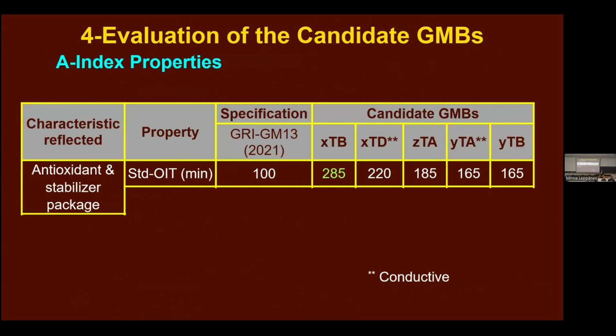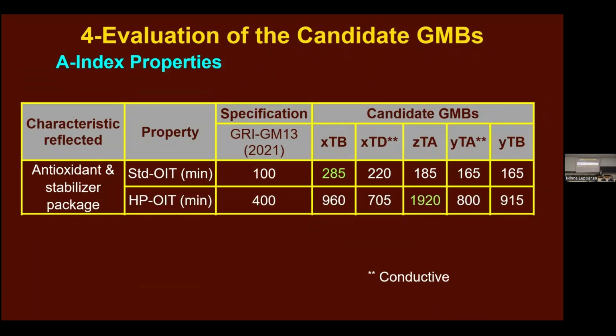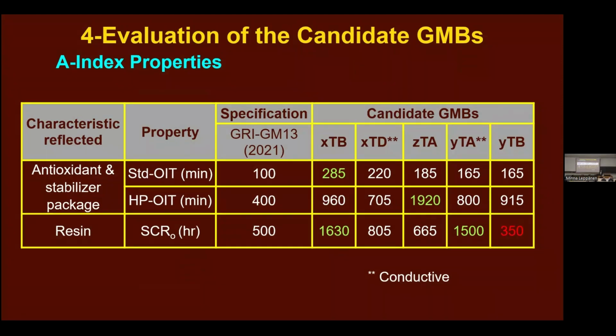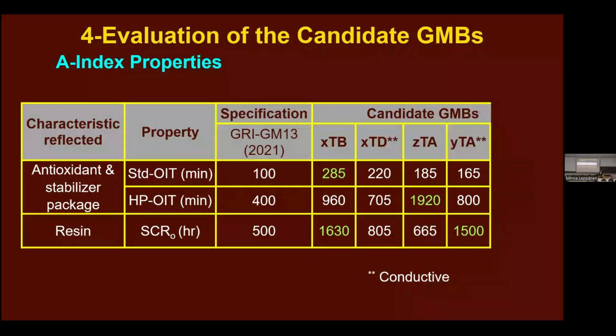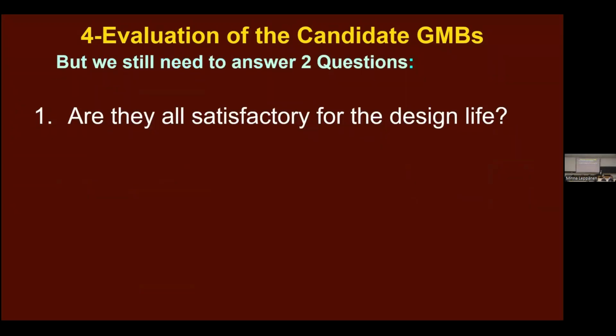So let's take some candidate geomembranes for a long service life. And you can see there the initial OIT values range from 165 to 285. This is the HPOIT, ranged from 700 to 1920. The resins, this is the initial stress crack resistance, range from 350 to 1630. Well, let's drop that one off. It's too low for stress crack resistance. Are they all satisfactory for a design life of 50 years, 100 years? Which is the best?